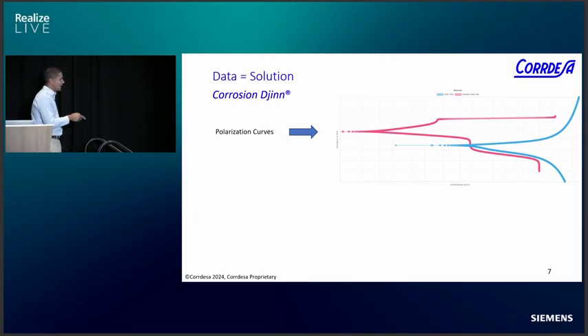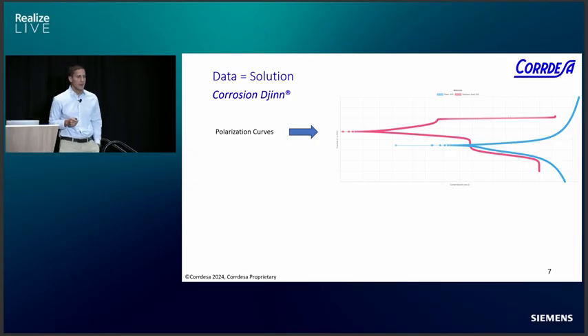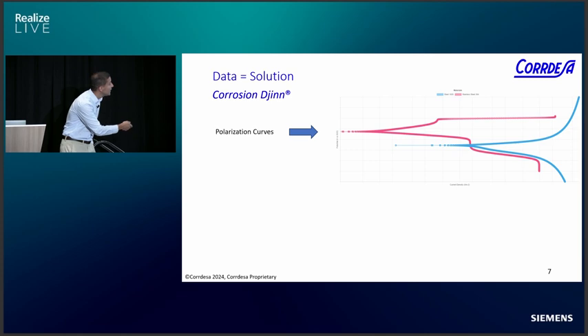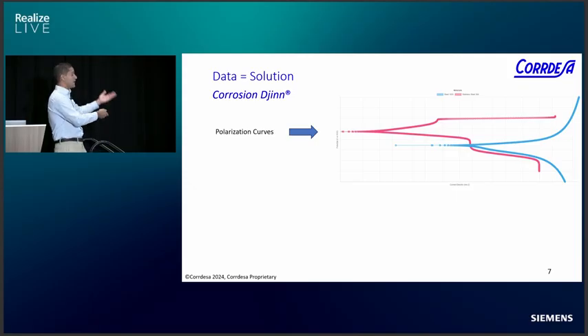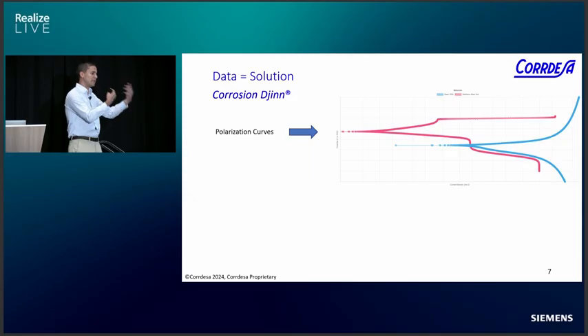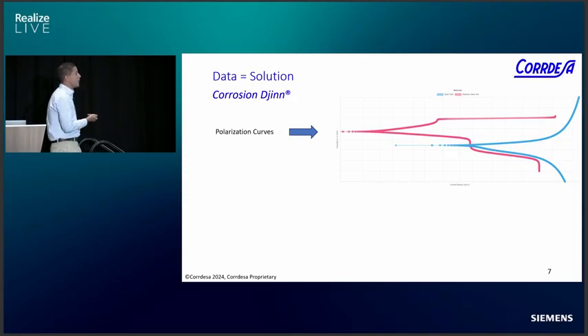This is exactly the same example I showed a few minutes ago about the mill standard. Exactly the same. So we have 1020, I think, yes, 1020 and 304. But we clearly see that this is a lot different from what we have in the table. However, this is exactly what the table represents, but we use the kinetics, the actual kinetics. And kinetics is extremely important here because depending on the film thickness, this branch over here, the cathodic branch, changes. It either shifts to the right or to the left. Therefore, it's really important. Similarly with the anode cathode ratio. We're going to see that in a minute.